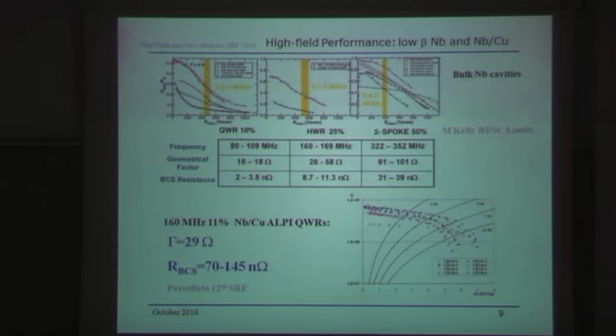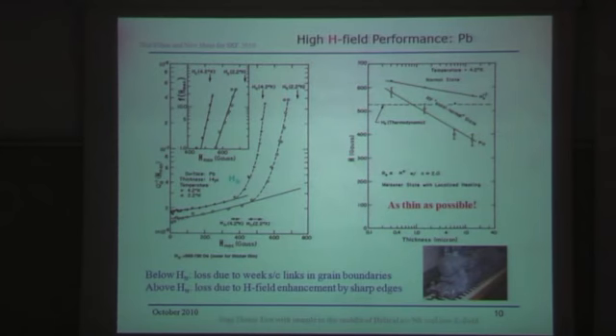So once again in lead, from Yogi's thesis, we still have an interesting transition. There is some transitional field which was contributed by weak links and grain boundaries, and above it was contributed by enhancement by sharp edges. And here I just show you a nice steam train which sort of represents lead technology.